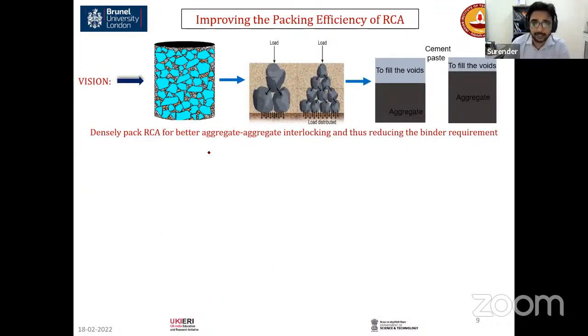As I mentioned, for pavement applications or special concrete applications, the aggregate to aggregate interlocking plays a vital role, right? So in that case, normally we have, say, 1 cubic meter of concrete. Most of the time, we use well-graded aggregate, so that when you are able to reduce the porosity with the help of the well-graded aggregates, the amount of cement required to fill these voids will be reduced. And we know cement is the costliest component. And that's how we can also improve the interlocking capacity of the mixes, right?